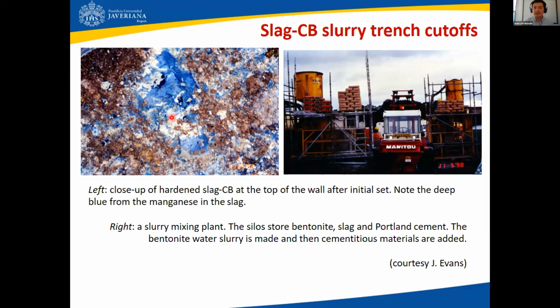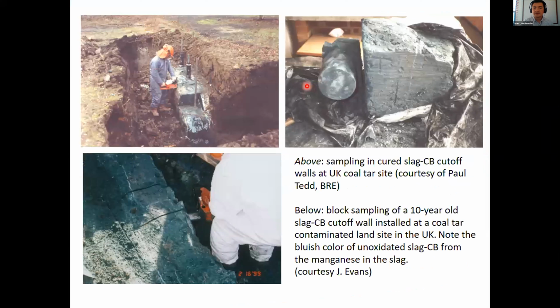On the right-hand side, what you see is a slurry plant or slurry mixing plant, which is rather small in size for this type of construction. The silos that you see here are where bentonite, slag, and Portland cement are stored. And the bentonite water slurry is made at this plant, and then cementitious materials are added. Finally, what you see here on these photos on the top is the process of sampling a cured slag-CB core of the wall. They are taking samples from an existing wall at a contaminated site with coal tar in the UK. And actually the photo on the bottom is also a sampling process from a 10-year-old slag-CB cutoff.